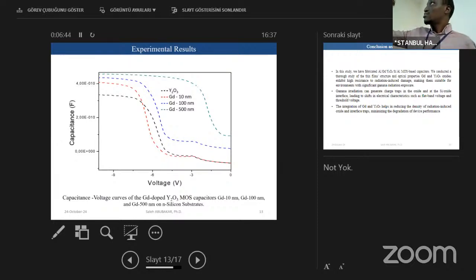For the gadolinium oxide, in sensor or detector technologies, sometimes low capacitance makes it easy to detect low radiation materials, but with high capacitance you can get high reliability, but the sensitivity is a bit low because you need more energy or more electric field, what is called a bias, to trigger that material to give you sensitivity. So here, as you can see, gadolinium oxide has high capacitance, but it's more reliable because the depletion layer starts at zero, which looks like what I call an ideal MOS capacitor curve.